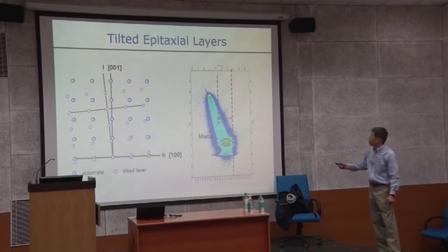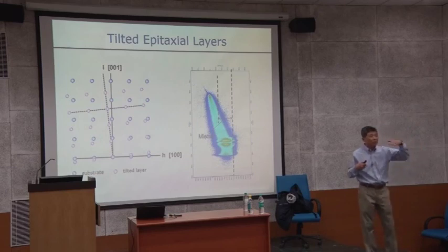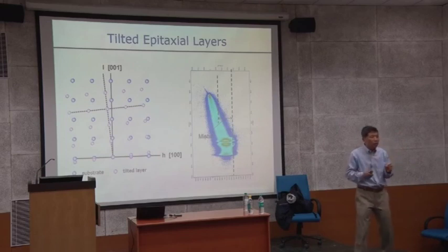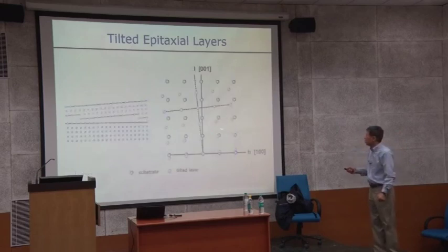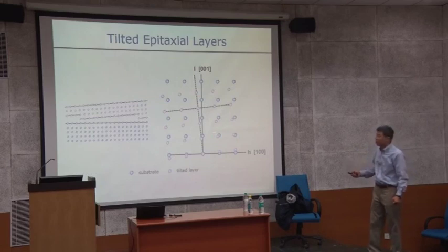This one is from here to here. This one is all lined up. The thin film is all lined up with respect to the substrate. The reason you have this one is actual tilting of the sample. It's not related to relaxation or anything, just simple tilting of the material. So you can tell either tilting or relaxation. I'm not going to go into all the details, but you're accessing one of those. When you scan a reciprocal space map, you usually do not scan this one, you usually scan one of these.